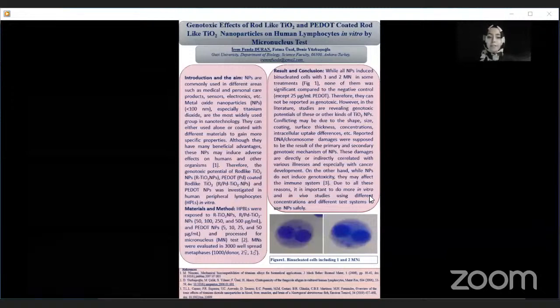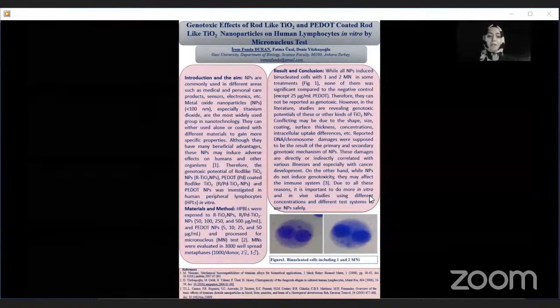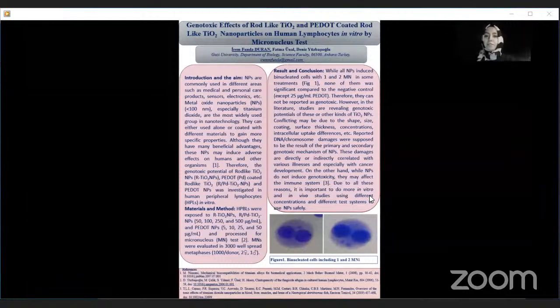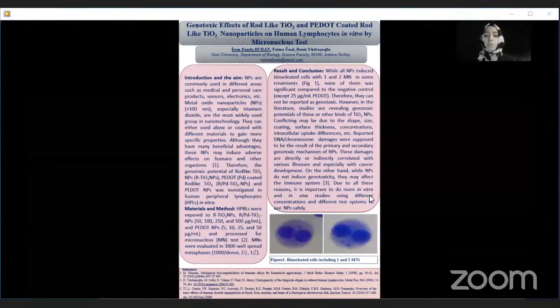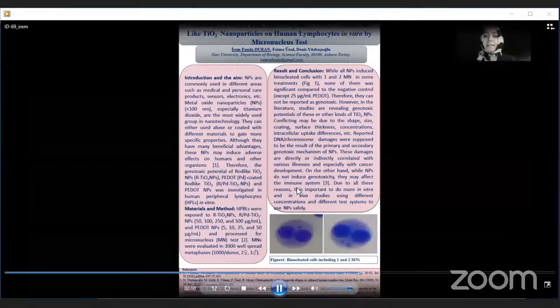PEDOT-coated rod-like titanium dioxide nanoparticles at 50, 100, 250, and 500 microgram per milliliter, and PEDOT nanoparticles at 5, 10, 25, and 50 microgram per milliliter, were processed for the micronucleus test. Micronuclei were evaluated in 3,000 binucleated cells. While all nanoparticles induced nucleated cells with 1 and 2 micronuclei in some treatments, none of them was significant compared to the negative controls, except 25 microgram per milliliter PEDOT. Therefore, they cannot be reported as genotoxic.